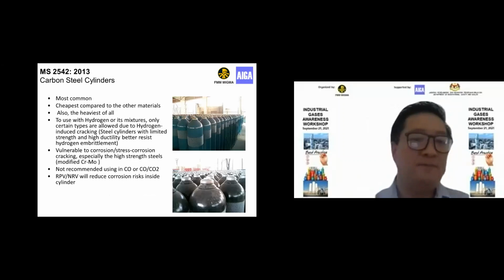Okay, carbon steel, most common, is the heaviest of all the cylinder types. It's used for hydrogen and its mixtures, but the material composition needs to be looked at. It needs to be able to withstand stress-induced cracking due to hydrogen embrittlement. So there is a special component that needs to be added to the material while manufacturing these cylinders. It's vulnerable to corrosion from moisture. Not recommended for CO and CO2 service. RPV or NRV valves, I'll go through later as well. These are recommended to ensure minimum internal corrosion due to ingress of air and moisture. Next.